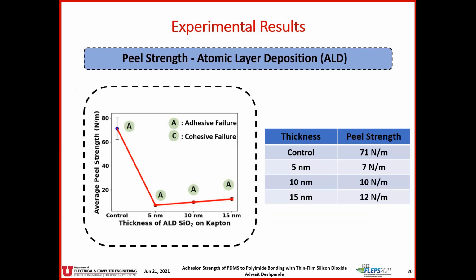All the samples for all three thicknesses of SiO2 deposited using ALD showed adhesive failures and bond strengths lower than control samples. The bond strength of the control sample was 71 newtons per meter, excuse me. The bond strength for 5 nanometer, 10 nanometer, and 15 nanometer samples were 7 Newton per meter, 10 Newton per meter, and 12 Newtons per meter, respectively.